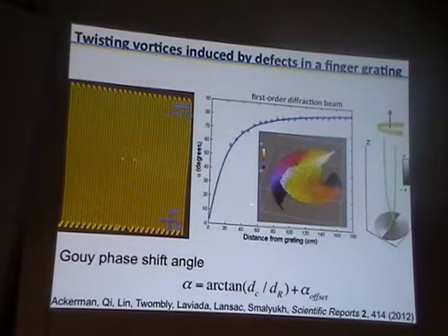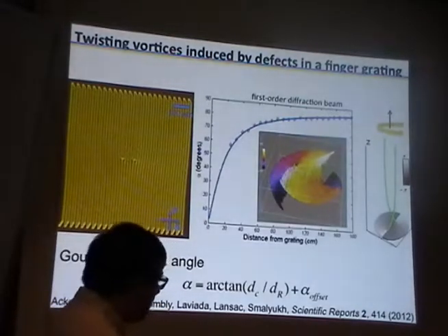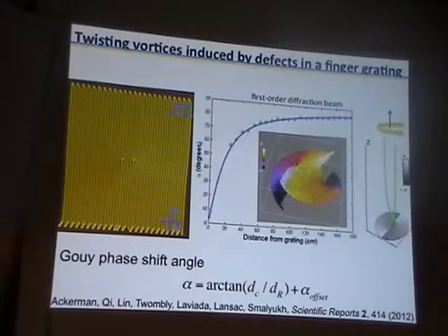So now one can generate a number of other different patterns and use them to obtain phase singularities in the diffracted laser beams. Here are some more examples. For example, when you generate edge dislocations with the same orientation of Burgers vector of those elementary edge dislocations, then the optical vortices that we would obtain would be rotating as a function of distance from the diffraction grating to the location in which you detect it.